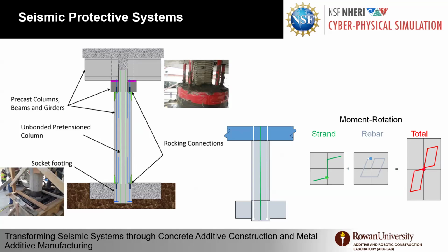We have a column end with rough surfaces that later have concrete cast around it for a socket connection. We also have end tubes to protect the concrete from spalling. We also have unbonded rebar for energy dissipation through yielding as the structure rocks. The top connection had reduced concrete section to accept the end of the pre-stressing. The rebar was also connected to the cap using holes that were all grouted together.